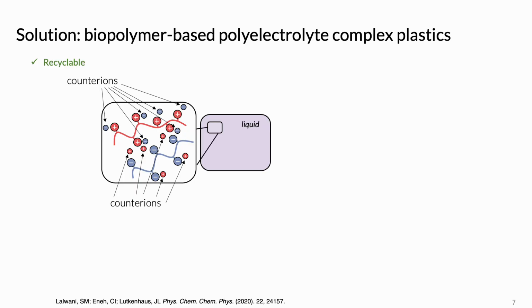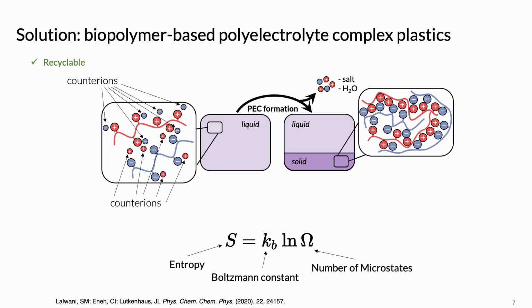You can see that the polycation with 6 positive charges also has 6 negative counterions. When we mix the oppositely charged polymers together, the change in entropy drives the separation of a polymer-rich solid phase out of solution. This is because entropy is related to the log of the number of microstates in a system, and the number of microstates in a system is directly related to both the number of orientations each molecule can have and the number of molecules in the system.